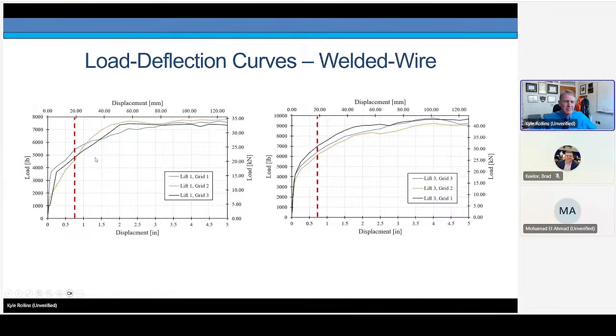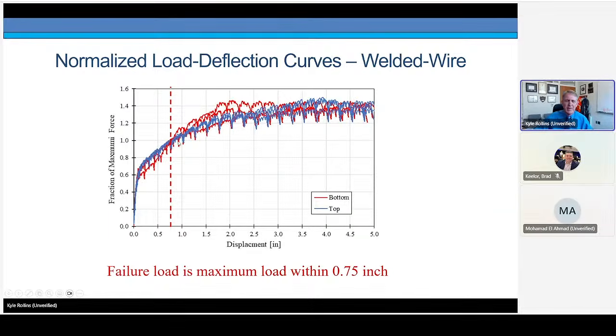In contrast, with the welded wire reinforcements, as we're loading them up, we get even more resistance as we displace the reinforcement. And at our value that we're picking off as our maximum here, within the maximum within 0.75 inches, we haven't developed the full resistance for the welded wire. And for this maximum, we might have an additional 30% resistance if you wanted to allow that kind of displacement to take place. We're trying to limit the displacement, so we use this value.